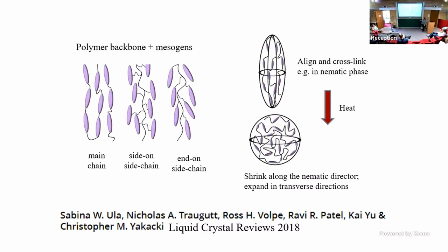Okay, and the key issue here is that you tend to get the materials to fabricate them and get the pattern in there. You essentially cross-link them partially is one way to do it, and then stretch them a little bit to align them, and then cross-link further. And then when you heat them, they shrink along the nematic director. There's actually a lot of different ways to pattern them. If you really want to know all of that, Chris Yakacki wrote a fantastic review in 2018. There's also a wonderful textbook about these materials by Warner and Terentjev.